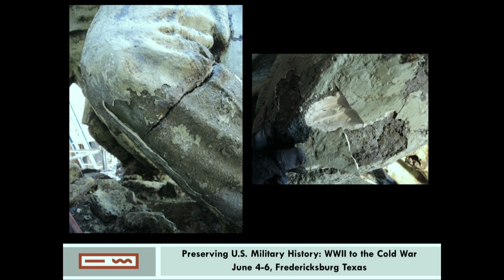After paint removal, a thick impermeable coating still remained on the surface, as you can see in this slide. This was originally thought to be the surface of the concrete as it was painted green, but was actually a thick combination of polyester and epoxy. This triggered a second phase of coating removal. You can see in the right-hand photograph there, it even filled patches. So there were massive holes, patches, cracking. This is probably from the manufacture or fabrication of the sculpture, but there were other areas that we just couldn't understand why there'd be a hole there. Probably it cracked during this. It was put on the back of a flatbed truck and trucked around the United States, so you can imagine what happened to it.